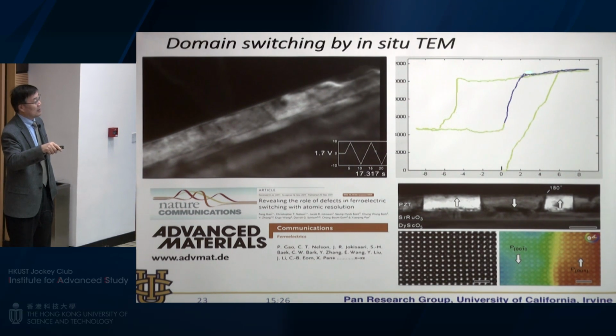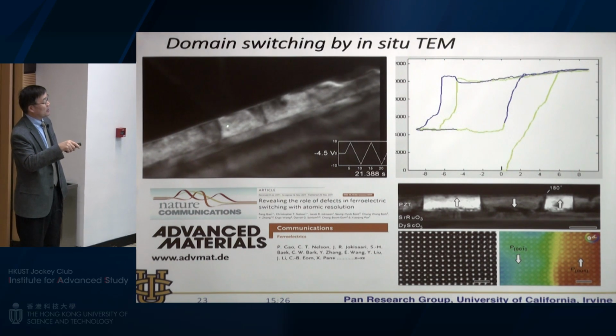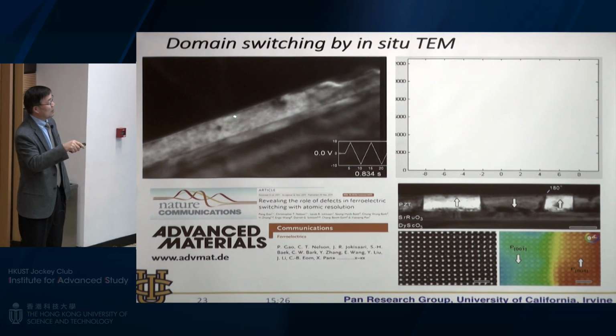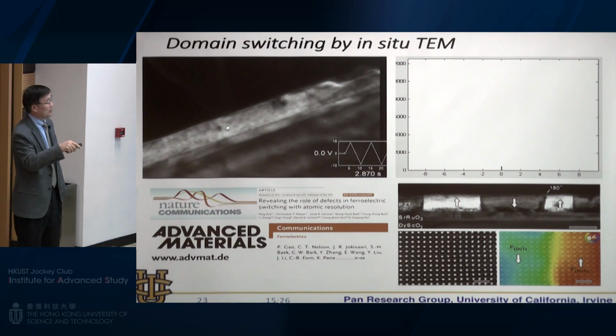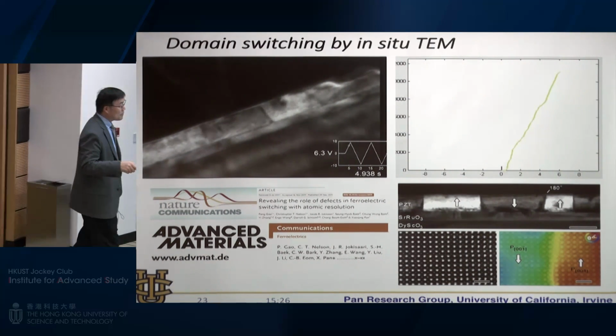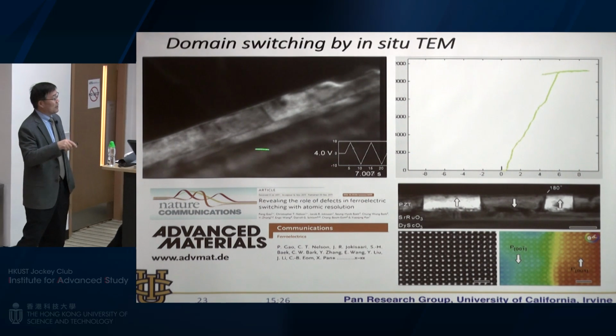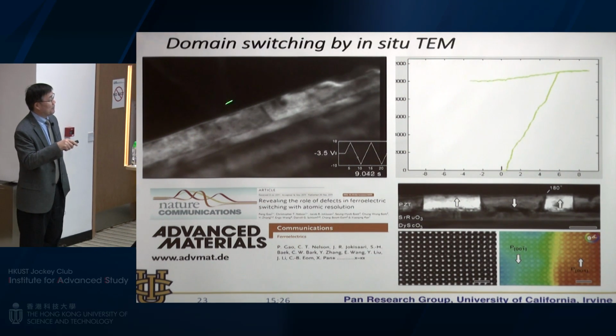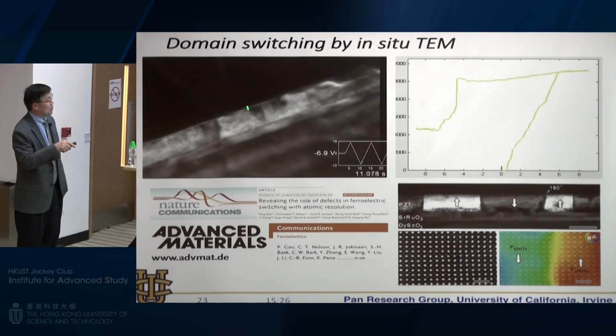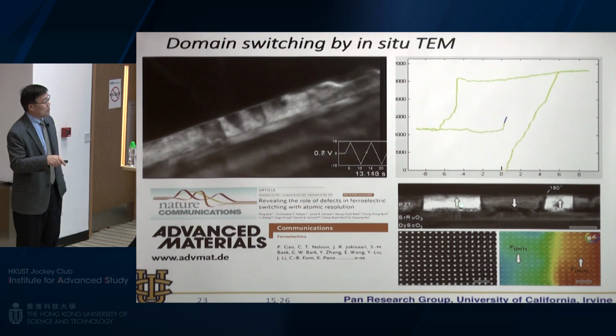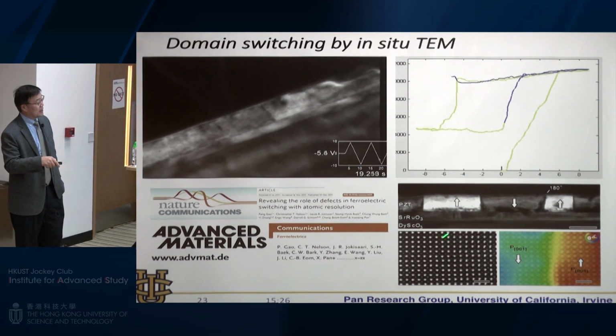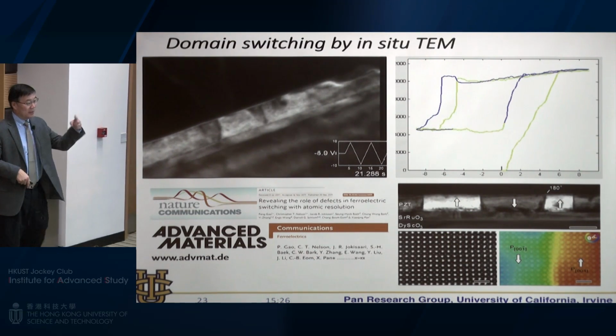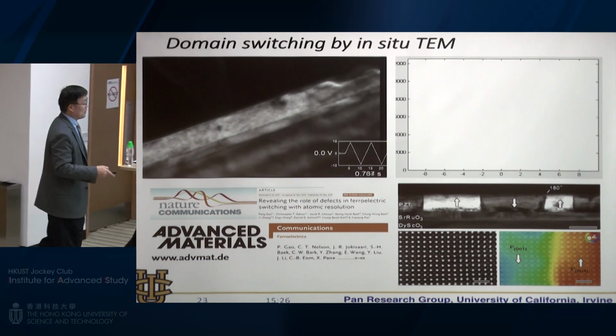You can see that this hysteresis loop is not repeating every time microscopically because the structure is every time slightly different, right? Depends on the contact. So in this way, you can study the dynamics of the phase transition and all the domain switching. And in the switched region, you can also determine the polarization using the method I explained previously, so that you can determine the dipole moment, orientation, and also the atomic scale mechanism.